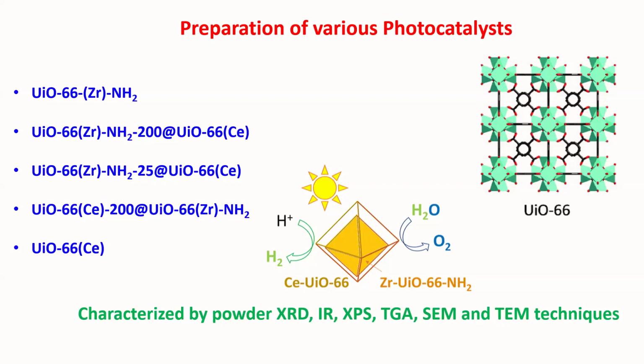So you have two sets of photocatalysts, and we have decorated one as a core and the other as a shell, and we wanted to test the activity of the solid in overall water splitting. Imagine that catalyst, and on the outer side is another catalyst. We wanted to make use of visible light or solar light as the light source to perform these photocatalytic reactions. After the preparation of these photocatalysts, they were characterized by powder XRD, infrared, X-ray photoelectron spectroscopy, TGA, SEM, and TEM techniques to make sure that the two solids exist as core and shell.